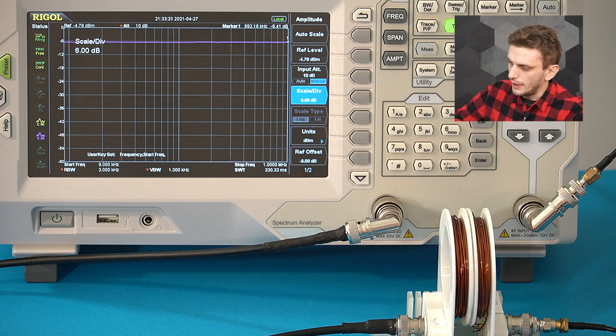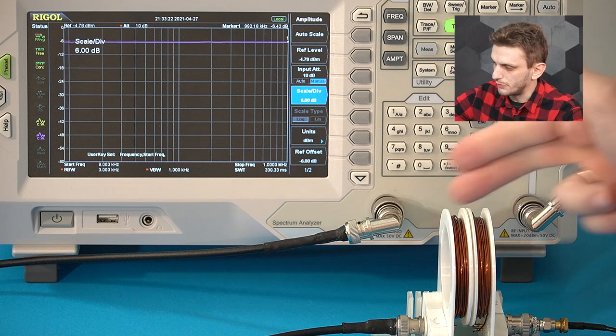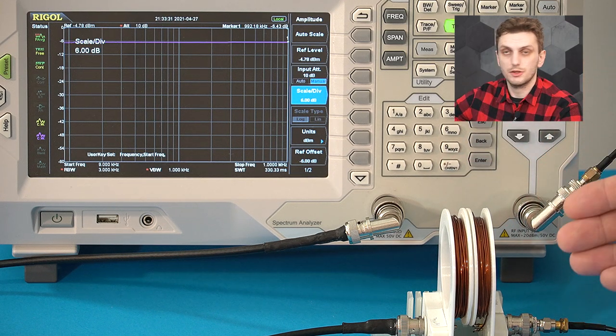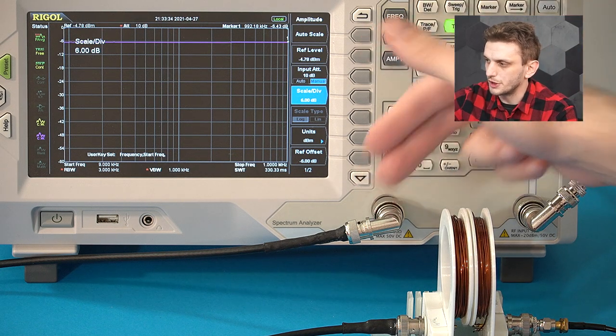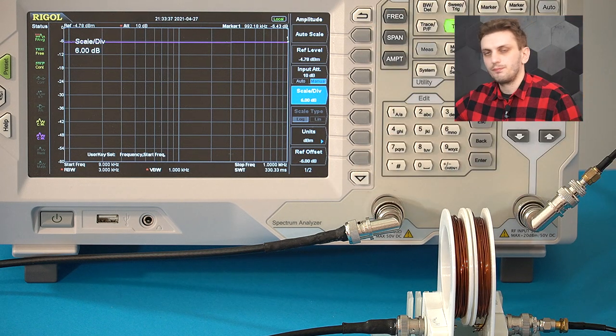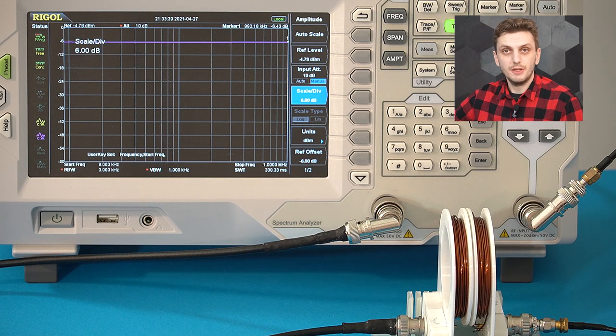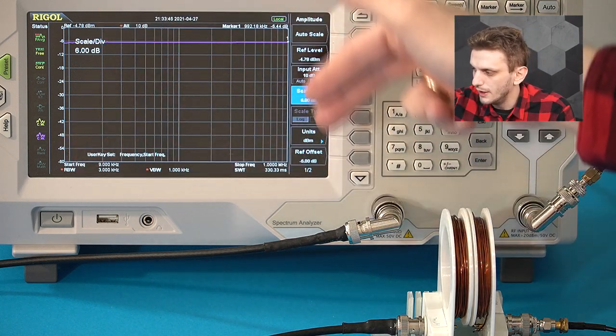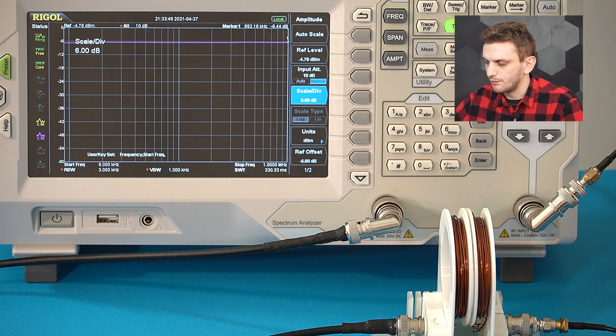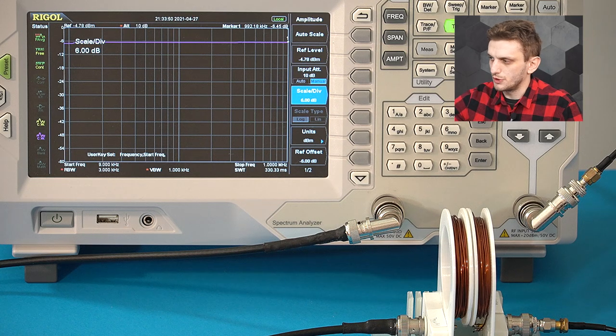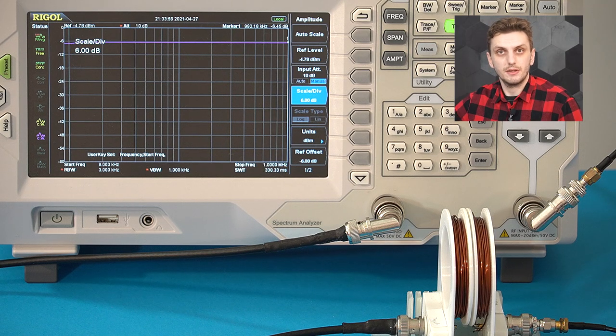To show off this effect, I prepared the same setup as before with my two coils. Rather than connect them to the signal generator and oscilloscope, I connected them to the spectrum analyzer with the tracking generator output. I want to look at the behavior of the shielding materials over a wider frequency range. I set the device to sweep from 9 kHz up to 1 MHz. Our first step was to normalize the response, so we have a flat response. By inserting the various materials, we can see how they affect the signal coming into the second inductor.